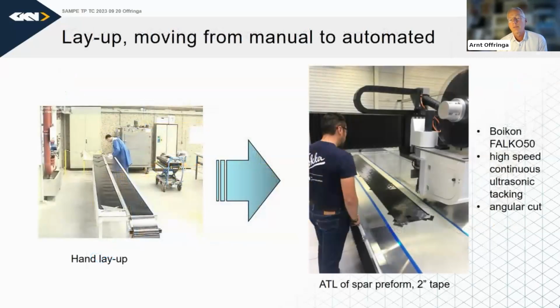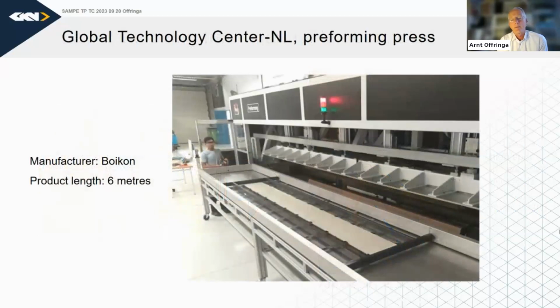And the process starts typically with a flat material. So on the left is the way we would do it several years ago, but on the right is using equipment, a machine, to lay down thermoplastic tape. It's 2 inches in width, or 50 millimeters, and it can be laid down at very high speed, up to 2 meters per second, and cut at an angle. And it uses ultrasonic energy to attach the layers to each other to make a laminate. And then the next step is to take this laminate into a press. It's a fairly simple pneumatic press with an oven behind it. So the material is clamped, as on the picture, then moved into the oven and then back into the press and quickly stamp formed into a shape, such as a spar.